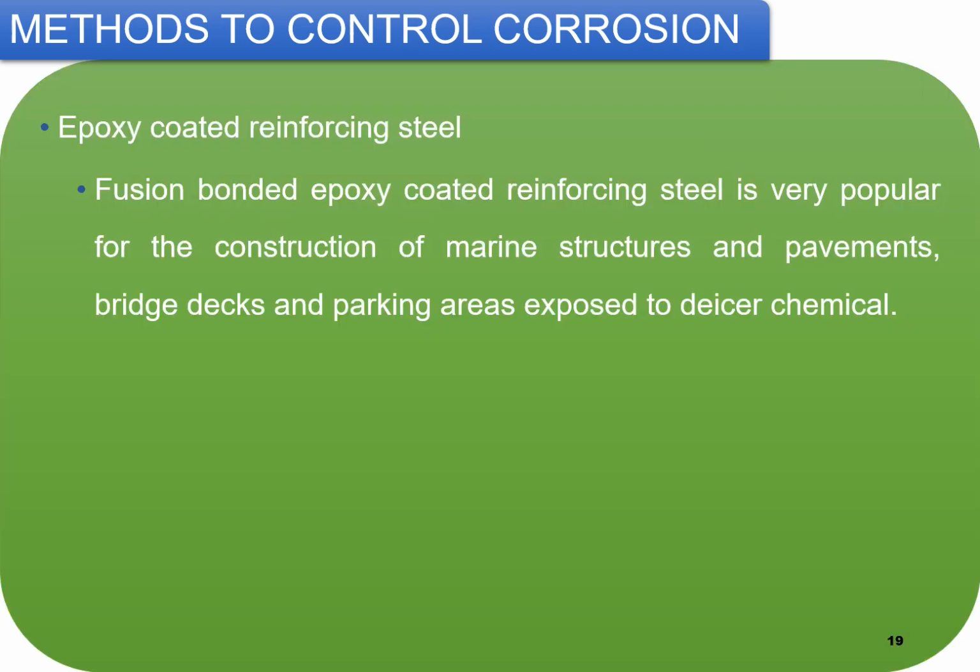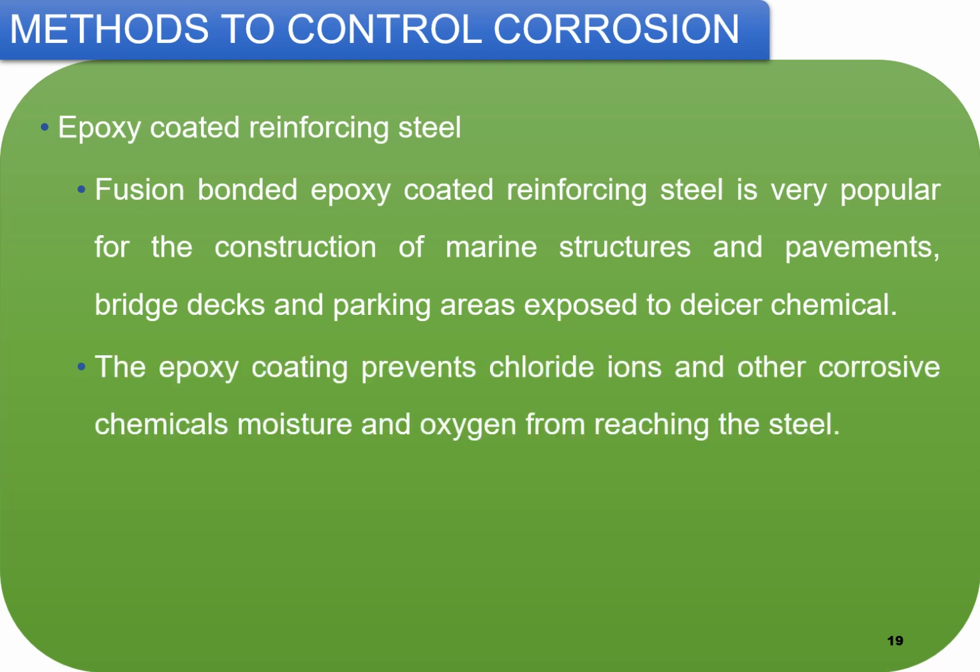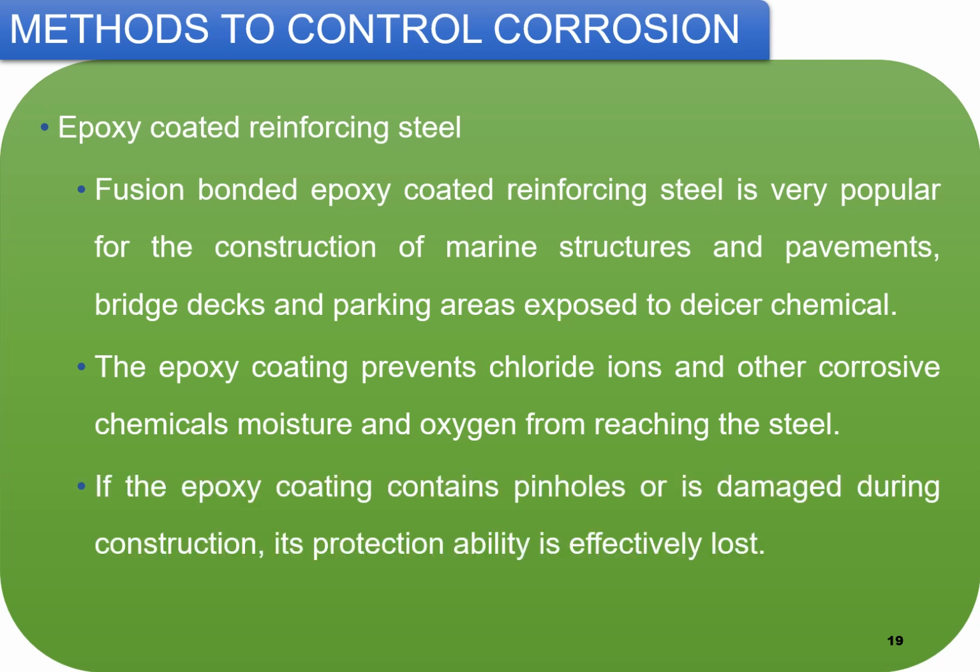Epoxy coated reinforcement steel is also one of the methods to control corrosion. Fusion bonded epoxy coated reinforcement steel is very popular for the construction of marine structures, pavements, bridge decks, and parking areas exposed to de-icer chemicals. The epoxy coating prevents the chloride ions and other corrosive chemicals, moisture, and oxygen from reaching the steel. If the epoxy coating contains pinholes or is damaged during construction, its protection ability is effectively lost.